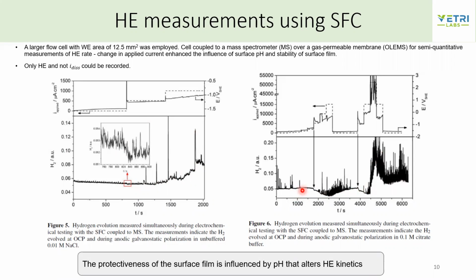Whereas in the case of buffered solution, what they found was quite interesting, because when they tried to increase the applied current, they found that the hydrogen evolution actually decreased in buffered electrolytes. All the fluctuations shown here they attributed to the formation of small bubbles from the surface; the release of attached bubbles gives fluctuations in the measurements. But what they were able to see is every time they tried to raise it to 5 milliamperes per centimeter square, the hydrogen evolution basically dropped, and it only increased when the dissolution current was more than, say, 15 milliampere per centimeter square.